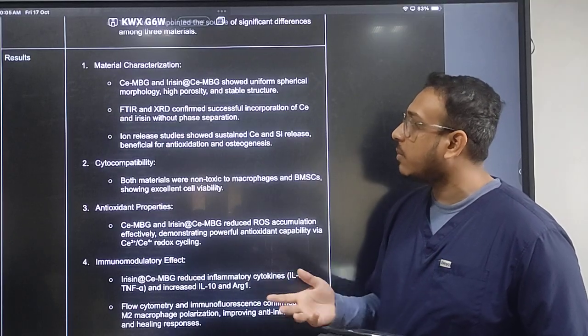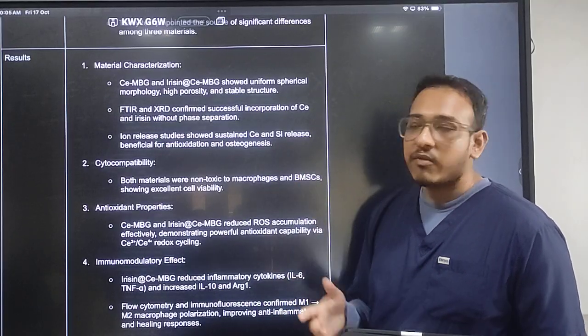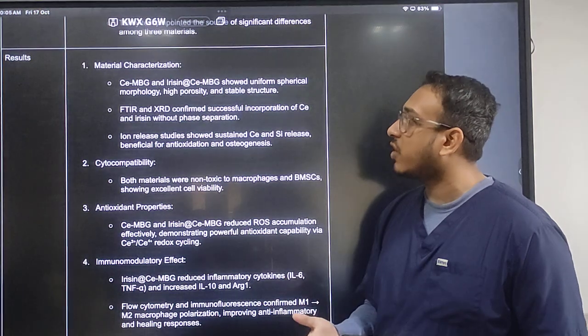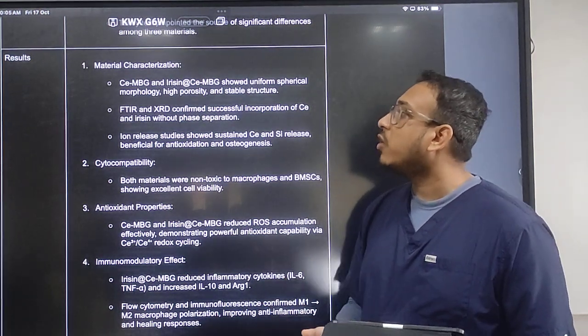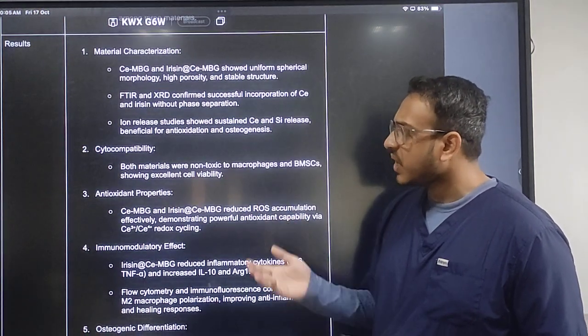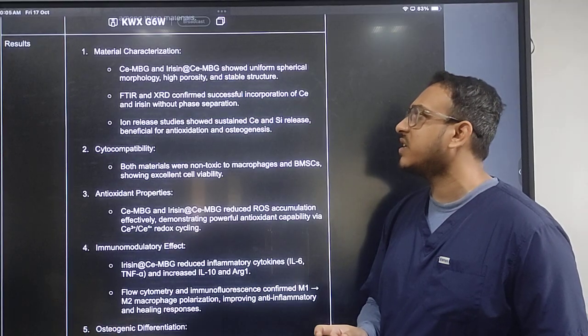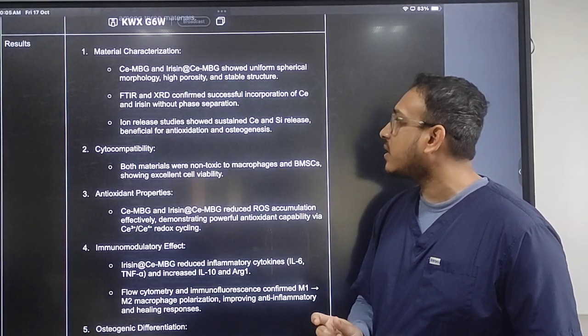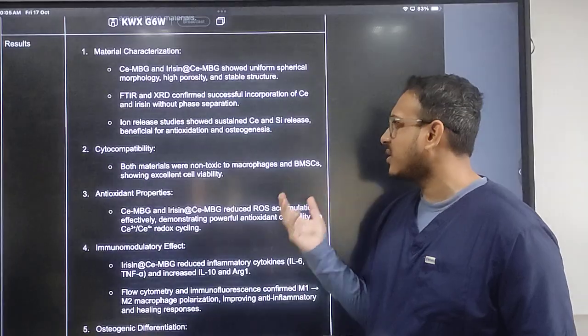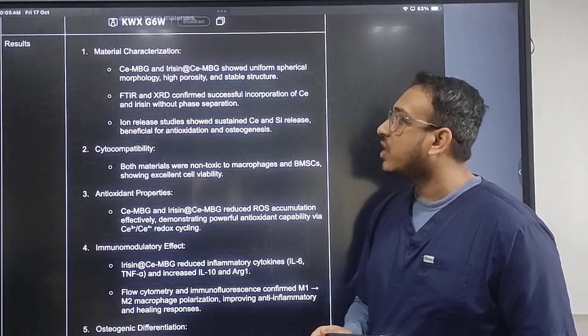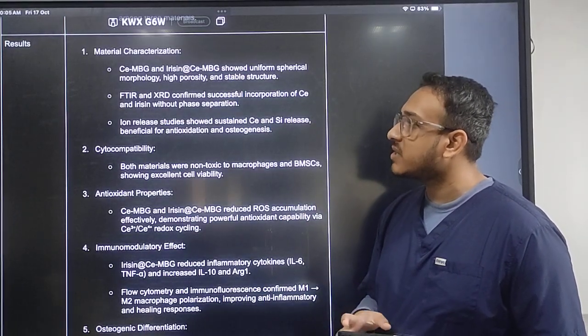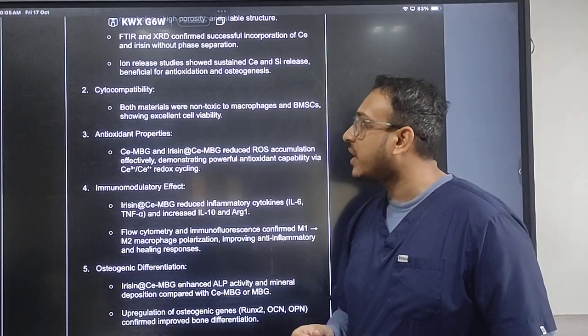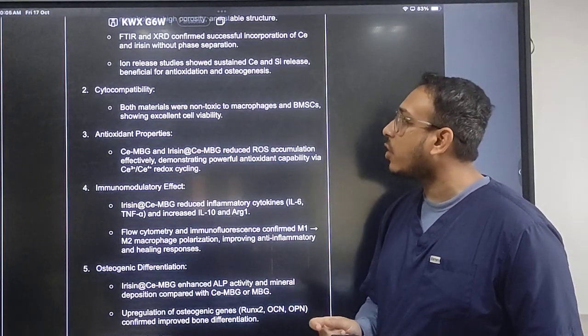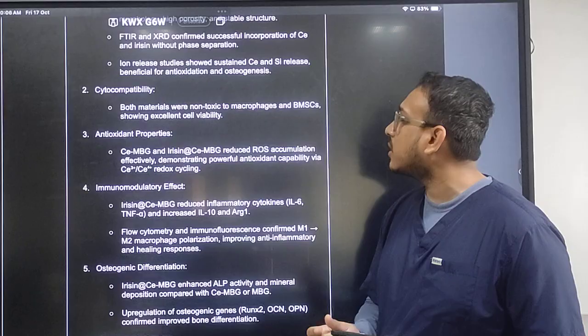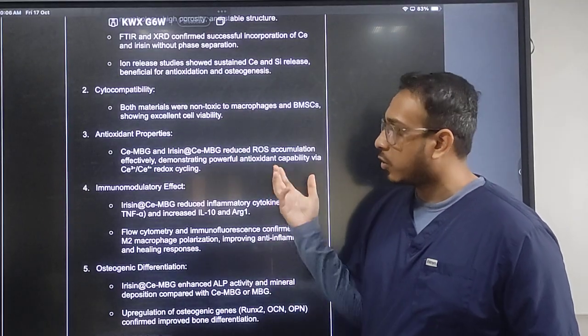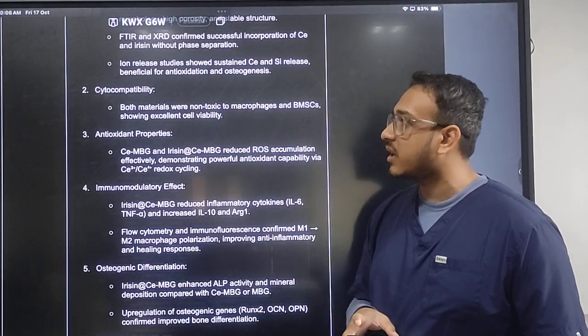porosity and stable structure. FTIR and XRD confirmed successful incorporation of cerium and irisin without phase separation. The ion release studies showed sustained cerium and silicon release, beneficial for antioxidation and osteogenesis. For cytocompatibility, both materials were tested to be non-toxic to macrophages and stem cells, showing excellent cell viability.